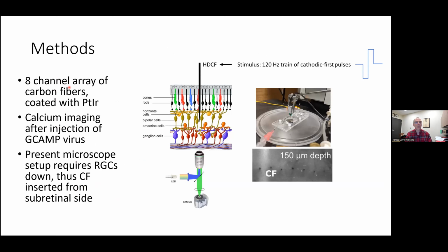So what we did here to start looking at this approach is we had an 8-channel array of carbon fibers, all coated with platinum iridium. In an in vitro setup shown here, we inserted those carbon fibers into the retina. And these retinas, a few weeks prior, had been treated with a mouse that we injected with the GCaMP virus. So now the retinal ganglion cells, because of the action of the virus, will be fluorescent, and that fluorescence will change based on the intracellular concentration of calcium.